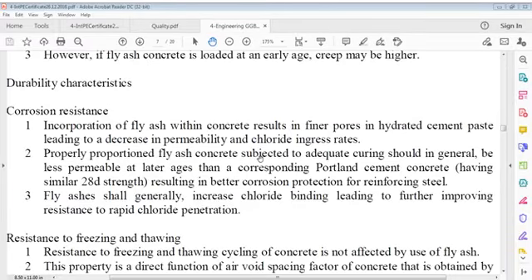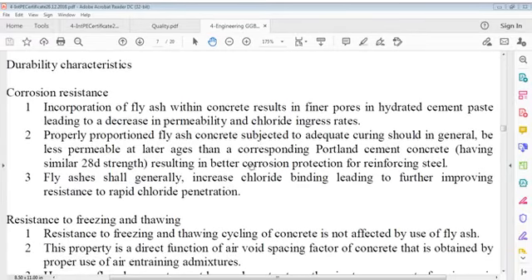So I come back now to corrosion resistance. I was talking about corrosion resistance, because in between I came to this paper, though it's an informative paper. It's a good one. Now, incorporation of fly ash within concrete results in finer pores in hydrated cement paste, leading to a decrease in permeability and chloride ingress rates.